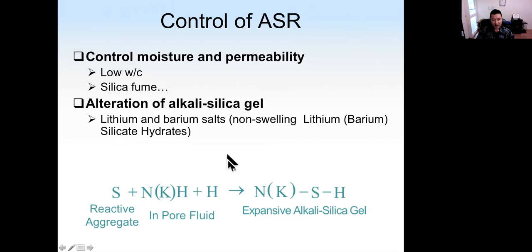From the mix design point of view, we can reduce the water to cement ratio. We can use silica fume to reduce the permeability of concrete and control the moisture. We can also alter the nature of the alkali silica gel. We have certain types of chemical admixtures such as lithium and barium salts. That type of salt will cause non-swelling lithium or barium silicate hydrate. So the gel will not be expansive and will not cause pressure in concrete, so no potential cracking.